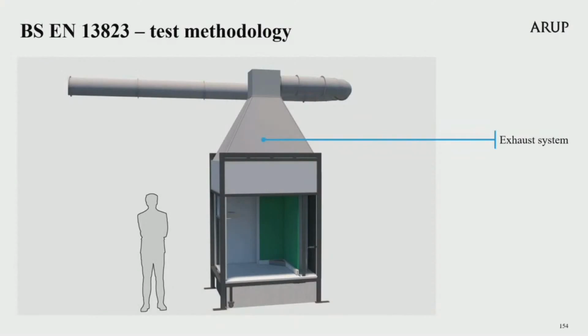An exhaust system is located above the test apparatus. In addition to the practical purpose of extracting smoke from a burning specimen, several measurements are taken in the duct exhausting the smoke. These are thermocouples to measure the temperature of the smoke, a pressure sensing probe to measure the flow-induced pressure difference in the duct, a gas sensor that measures the oxygen and carbon dioxide content of the air being extracted, and a light source and light sensor that shines through the smoke to measure how much light is being blocked, hence how dense the smoke is.